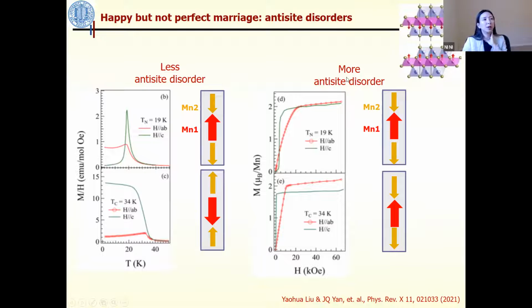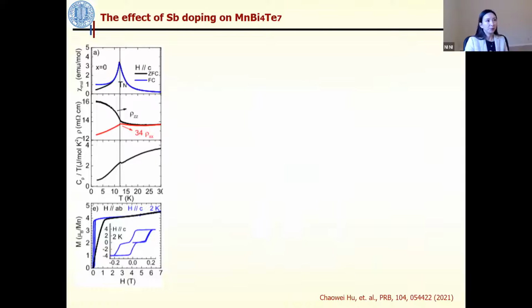However, once you have more antisite disorder, your sample becomes ferromagnetic-like. Your manganese 2 becomes ferromagnetically ordered, your manganese 1 becomes ferromagnetically ordered, but still the manganese 1 and manganese 2 are antiferromagnetically ordered. So this was a little background here.